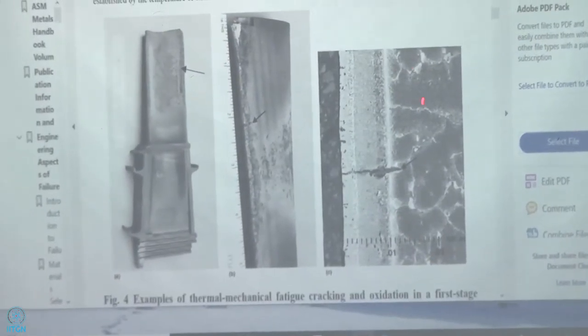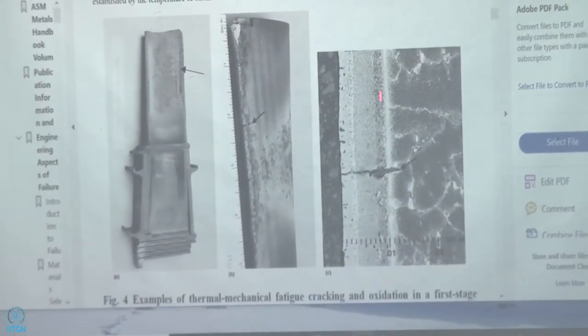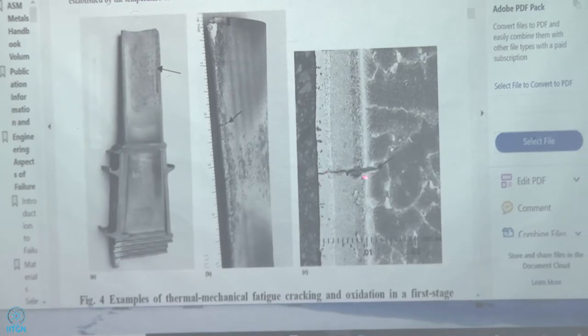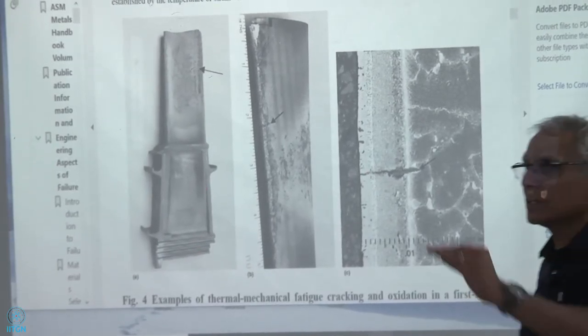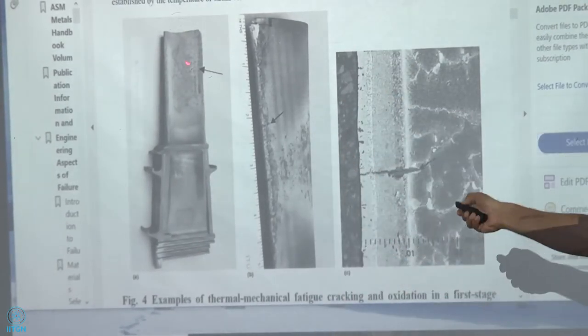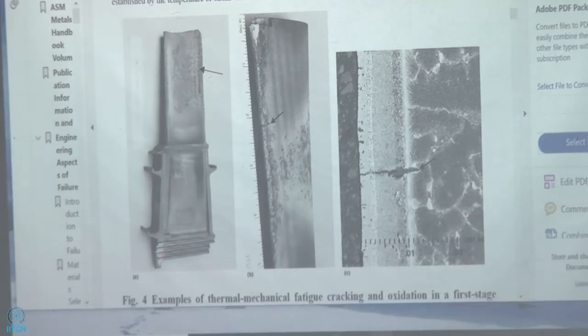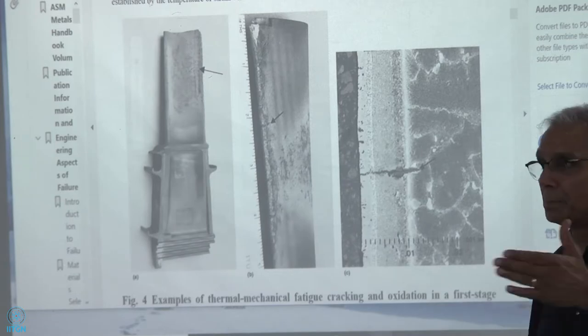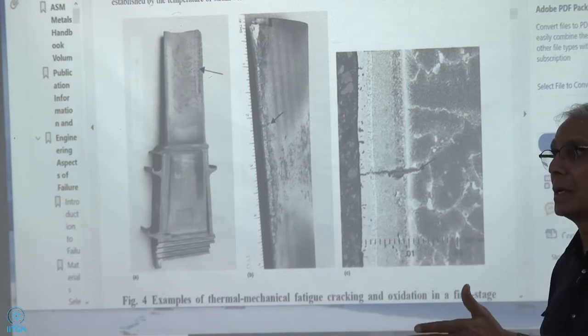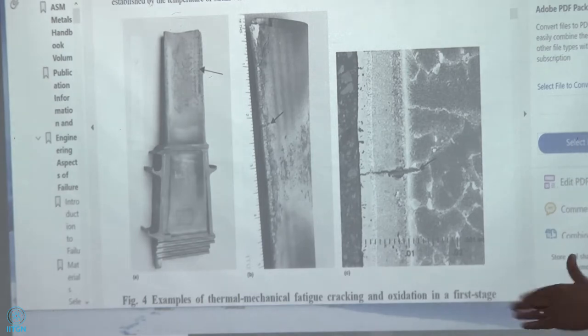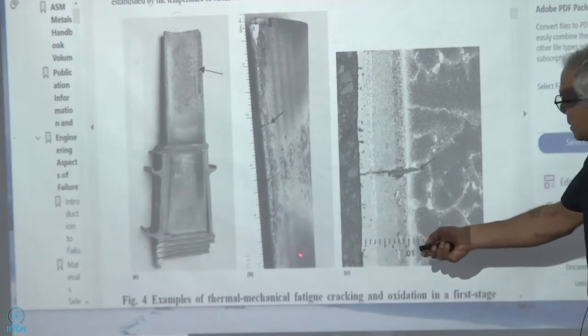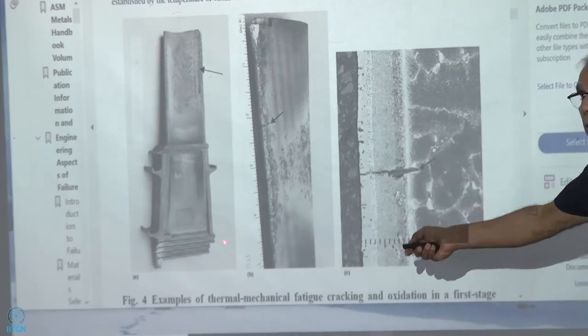Let's go through this, and I'll talk about that in a little bit more. After a break, we'll go through this first. Alloy composition: we already said that those containing a high volume fraction of the HCP phase are susceptible to dwell fatigue, okay? And low volume fractions of beta BCC phase. And the most susceptible alloys contain clusters of alpha grains that have small misorientations with them, the micro textured regions.